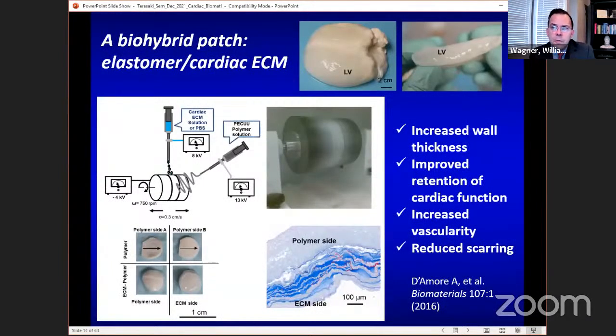Okay, so bioactivity. One regulatory-wise attractive thing to do is to work with decellularized matrices. And I live down the hallway from Steve Badylak, who many of you know. He's a pioneer in decellularized matrices, and he's been working a lot with hydrogels derived from ECMs, from extracellular matrices. And we worked with his group, and we're decellularizing hearts and then making a hydrogel from this by enzymatic degradation into hydrogel. And then we took that cardiac ECM hydrogel and we electrosprayed it while we were electrospinning polyester carbonate urethane urea.